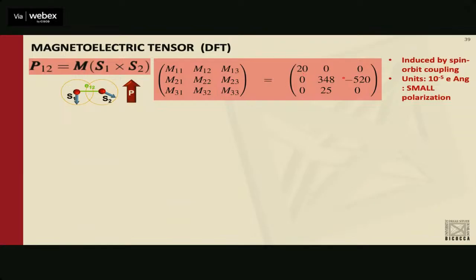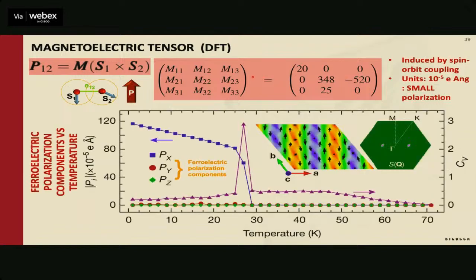And again, the effects are small, right? You shouldn't expect strong effects here because it's the spin that produces ferroelectricity. But still, you can expect some polarization emerging from the helix. Again, you can do Monte Carlo to go to the finite temperature range, and you can see that below the Néel ordering temperature, you have the emergence of ferroelectric polarization given by the